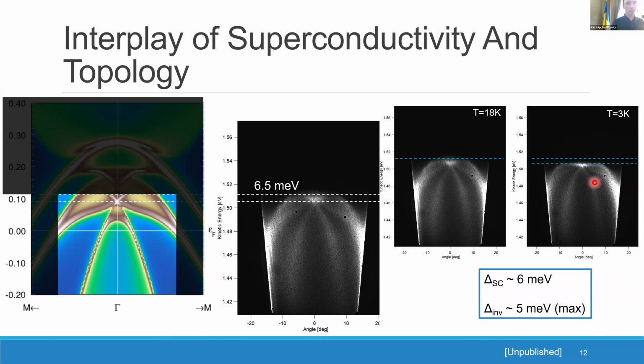And from this comparison of data to, again, some DFT calculations, these ones, I think the mouse is not working. This one is done by Klaus Koepernik. The previous one is done by Alexander Yaresko. So this is the band structure integrated over the whole Brillouin zone, and you can even see kZ broadening here, because different points, gamma point, Z point, they all align here. And it's nice that in laser ARPES we also see this kZ broadening here. So it's also quite a unique result if you compare it to the literature.